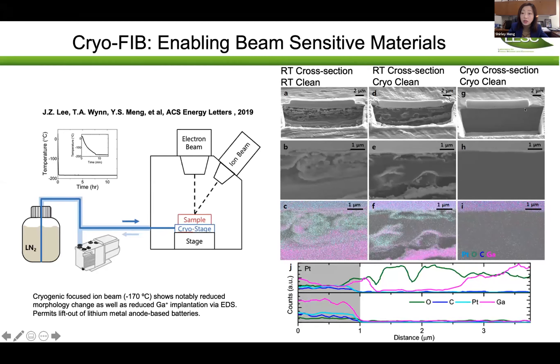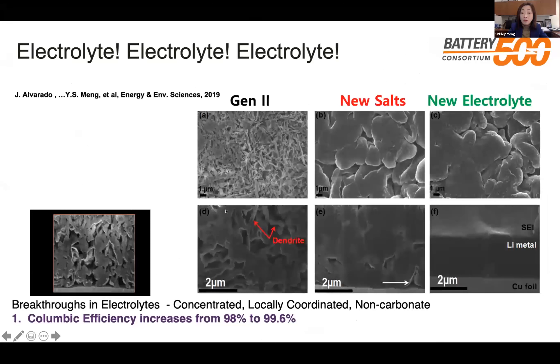Moving to cryogenic temperature significantly reduces the reactivity of lithium metal, and that's where you can actually see very nicely preserved morphology. This lithium was vapor-deposited and should be dense without any pores. Almost all phenomena observed with room-temperature FIB-SEM are basically artifacts.